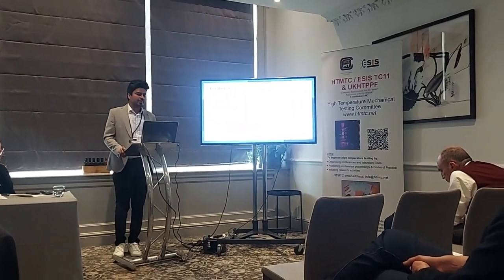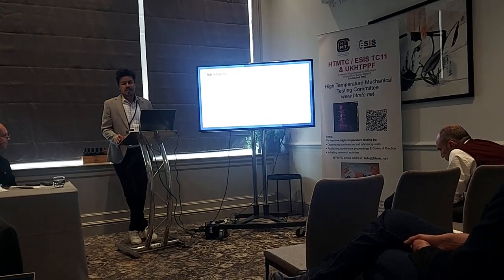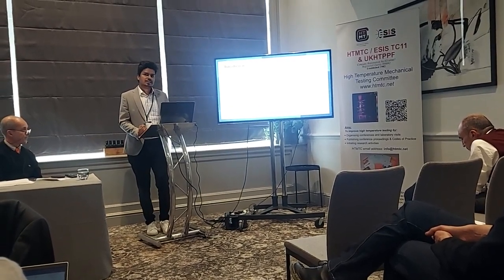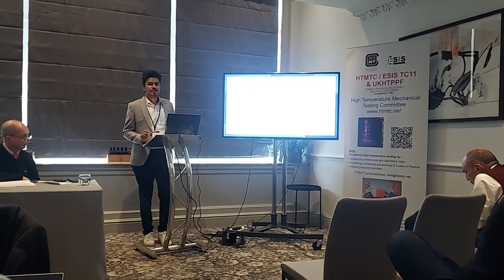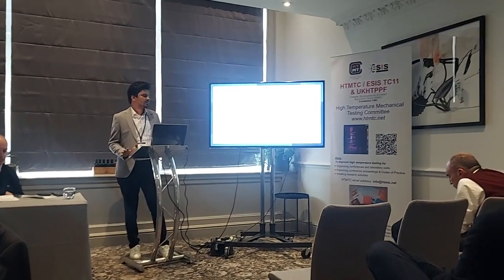To begin with the introduction, many components in nuclear power plants undergo creep deformation due to elevated temperature. To assess their life, we have to understand their creep behavior under creep conditions. The common test technique available is the uni-axial creep test, but this comes with certain restrictions — specifically, the requirement of a significant amount of material for testing, which may require the entire facility to be shut down. To overcome this drawback, a revolutionary, efficient, and cost-effective technique was introduced in 1981 by Manahan: the small-punch creep test. A major advantage is that it uses a very small amount of material, making it a non-destructive test technique.